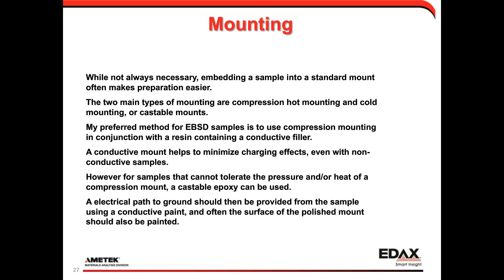And so there are really two main classes of mounting. There's sort of the compression hot mounting, and then there's the more cold or castable type mounting material. I've put here my preferred method is to use compressive mounting. I do this in conjunction with a resin that contains a conductive filler, and the reason for that is just to help manage the flow of electrons from the electron gun to the sample to ground to minimize charging effects. And we'll talk later in this presentation about charging. And so by using a conductive mount, I'm hoping that helps minimize charging effects.